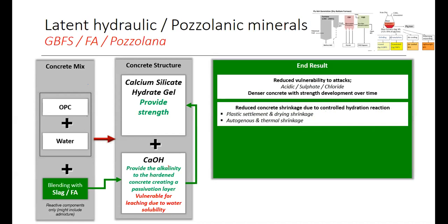And it reduces concrete shrinkage due to the controlled heat of hydration, because usually in the concrete industry, they use slag and fly ash as supplementary cementitious materials. They can reduce the amount of cement because slag or fly ash also delivers additional strength. They don't want to deliver additional strength; they maintain the same strength level by reducing the amount of cement added to the concrete.